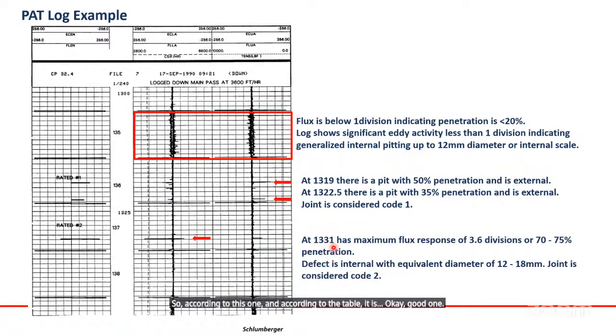At 1331 there is a maximum flux response of 3.6 divisions, or 70 to 75% penetration. The defect is internal. As you see here, the flux is showing and the eddy current shows, so it is an internal one. According to the division, it is 12 to 18 millimeter, and the joint is considered code 2. Any questions here?